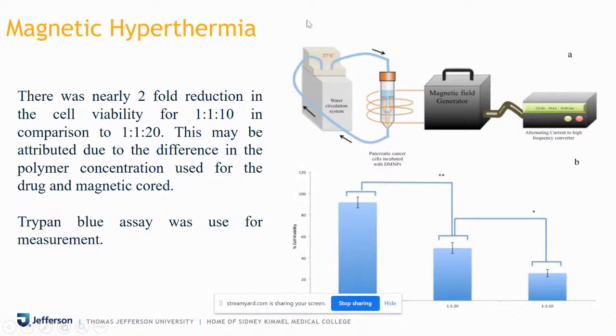The experimental setup that we had was a circulating water bath going through the tube, and you can see the 50 ml Falcon tube had three smaller Eppendorf tubes filled with the cell suspension treated with drug-loaded polymeric magnetic nanoparticles, and they were exposed to this magnetic field generator. Within 5 or 10 minutes, we could see a reduction in the viability of the cells. The untreated system had a viability of around 100%, whereas both the treated ones reduced substantially, which confirmed that magnetic hyperthermia was killing the cells by generating localized heating inside the cell suspension treated with these nanoparticles.